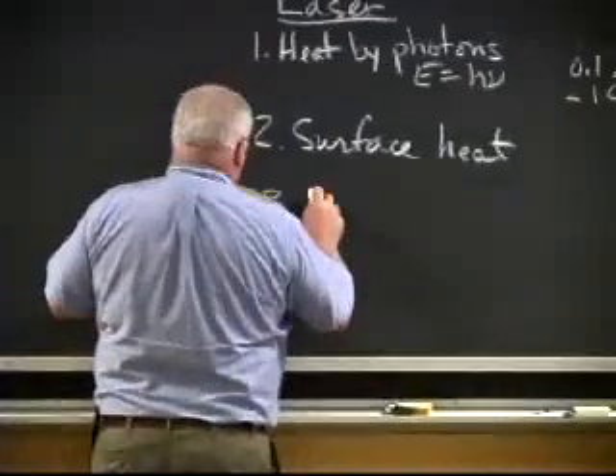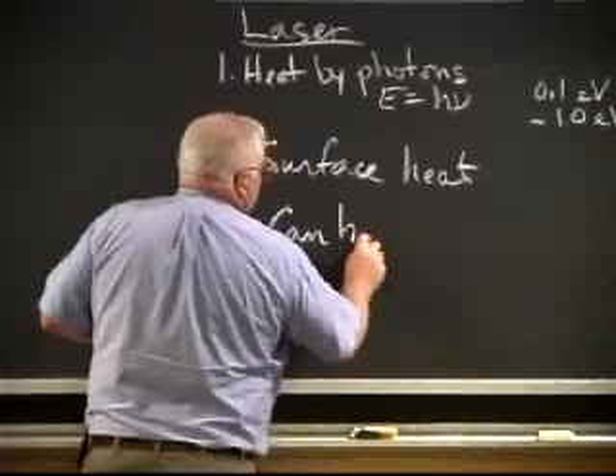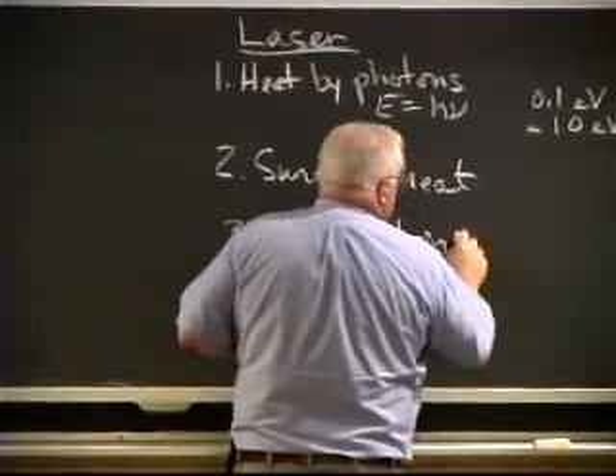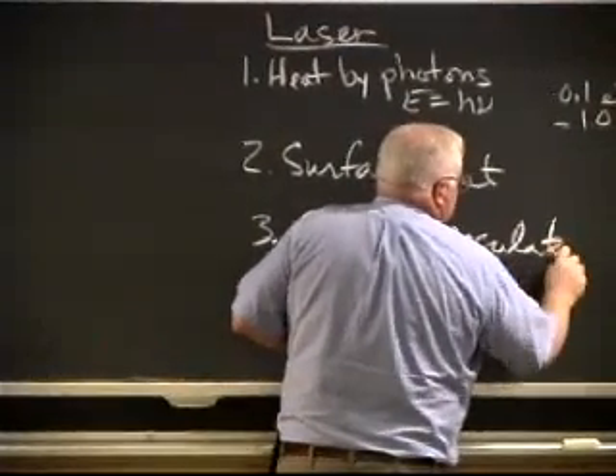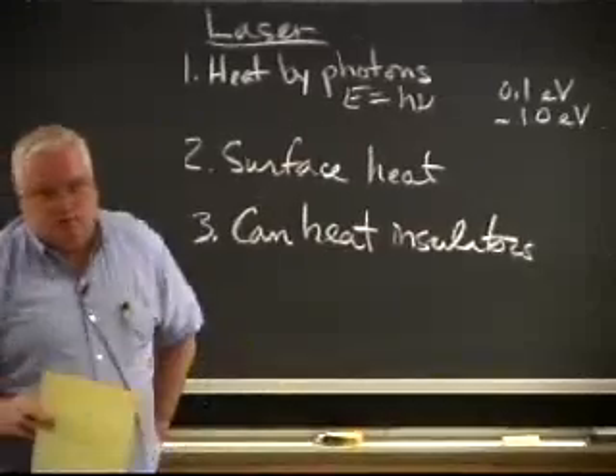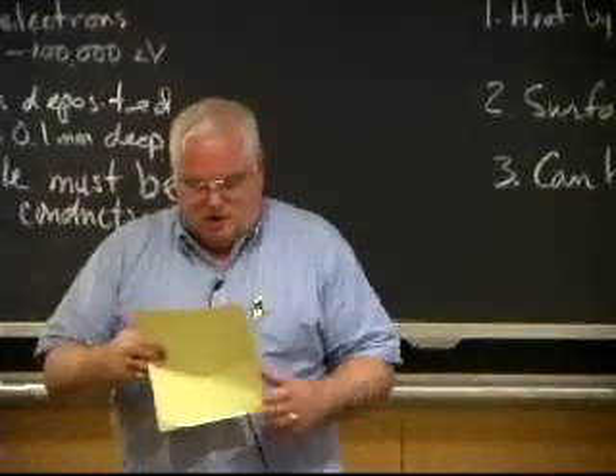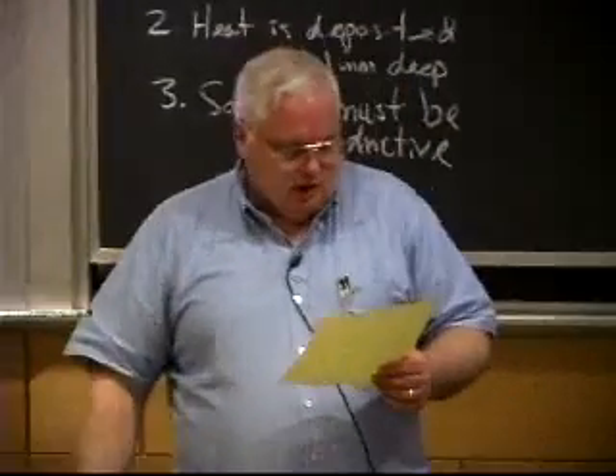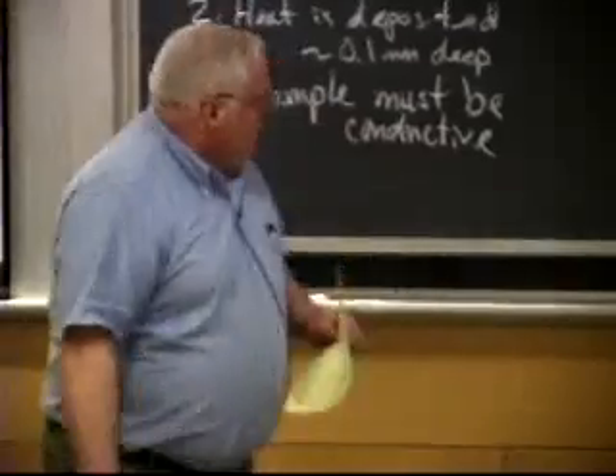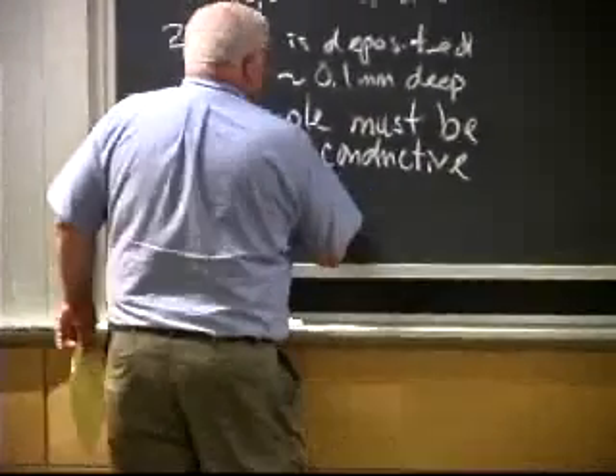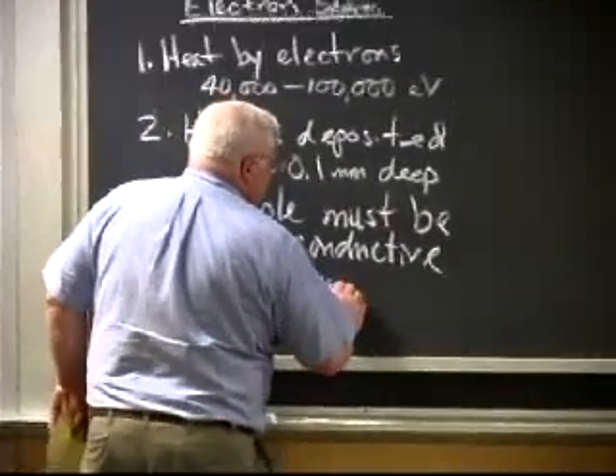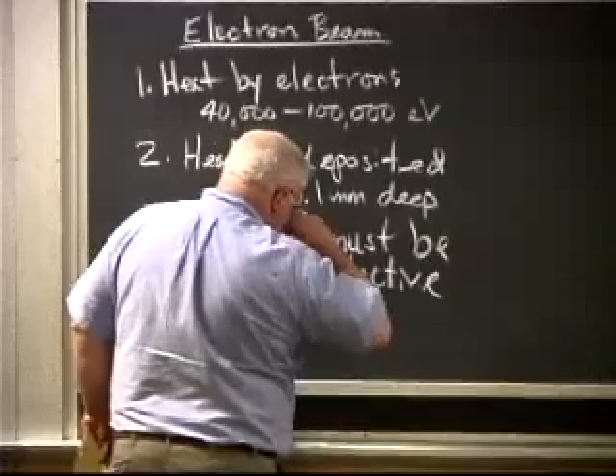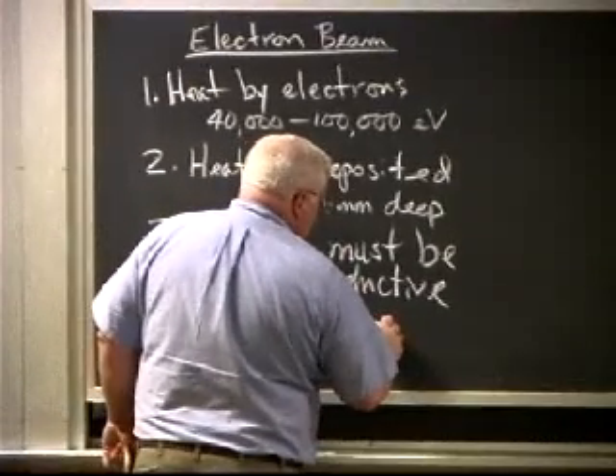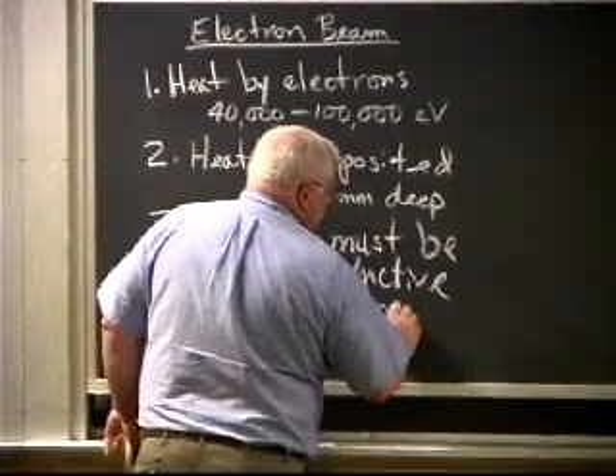Here, you can heat insulators. In fact, we'll see you can actually heat insulators even better with a laser than you can a conductive material. So far as making the material conductive, you can actually electron beam weld ceramics by preheating them.